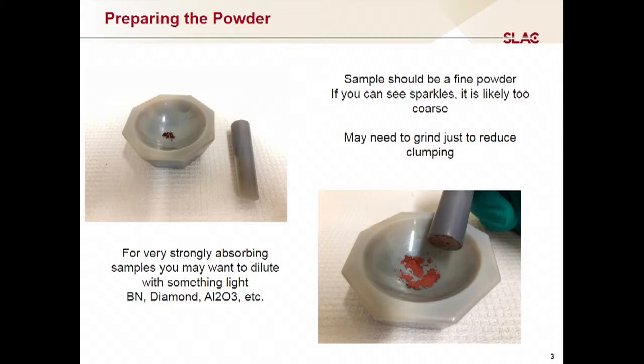You can take two different small molecules that may both be drugs. One may be a drug and one may be something else that, for whatever reason, you like to administer together. And it turns out that if you mix two of them in a mortar and pestle and you grind them together, sometimes by adding a little drop of solvent as you do so, you actually form a new crystal structure that contains both molecules crystallized into one phase. And so you want to be very careful that if you're just trying to prepare a known sample, or a sample that you have for powder diffraction, that you're not making something new as you're going through this process.